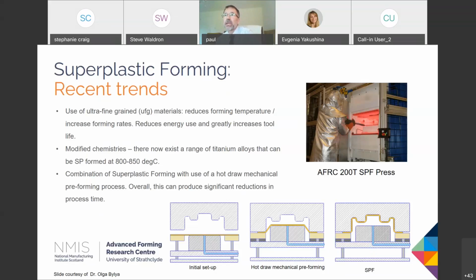Final point on that slide. This is still really at a research stage. I'm not aware of anybody using this industrially, but people are investigating the use of hot drawing combined with superplastic forming, as you see demonstrated in the schematic at the bottom. And what's going on here is that we're using a deep drawing process to put in most of the deformation fairly quickly, and then we just take advantage of the superplastic properties of the material to actually do the final part of the forming operation, where we really want to get that detail and generate the sort of complex geometries. The combination of the two produce some fairly marked reductions in cycle time for the process. If we jump to the next slide, Steph.